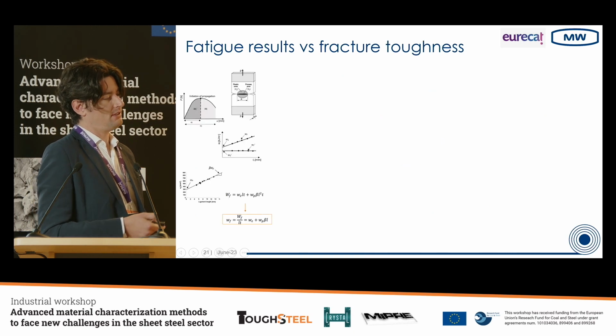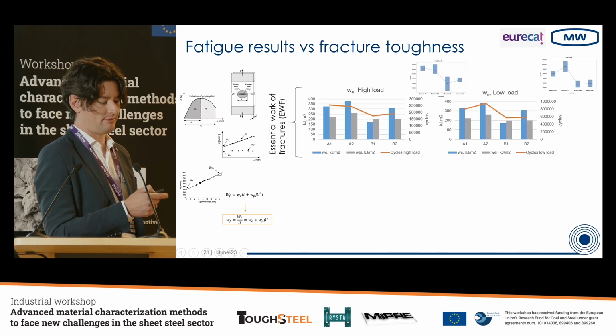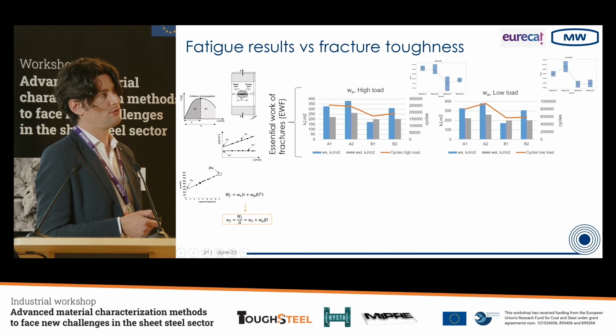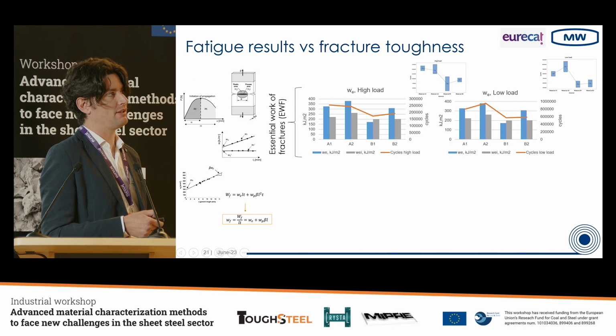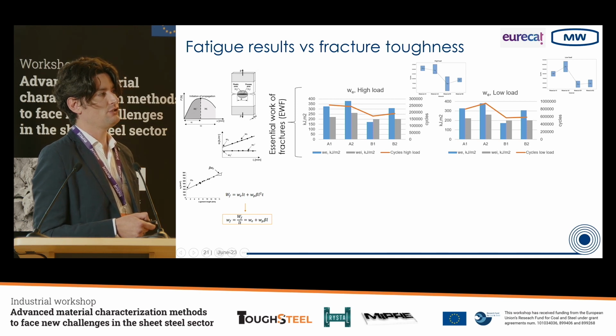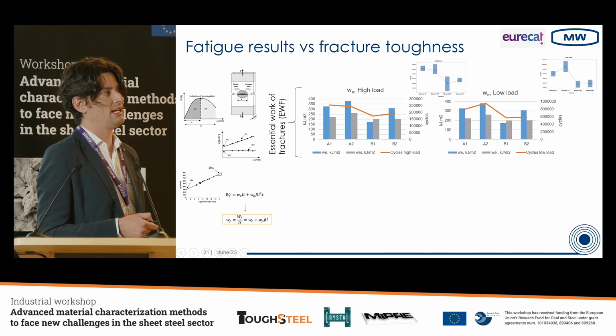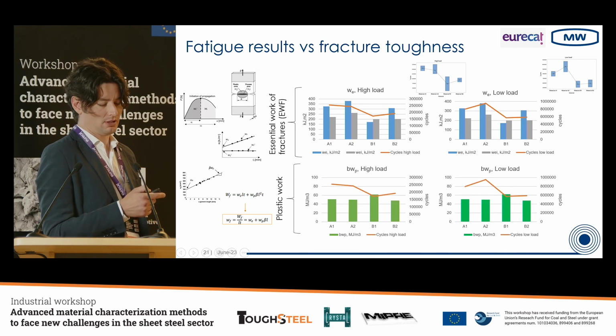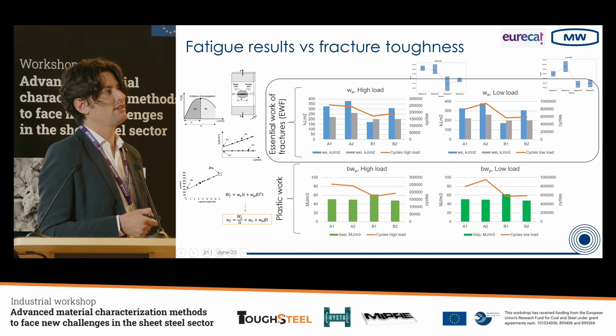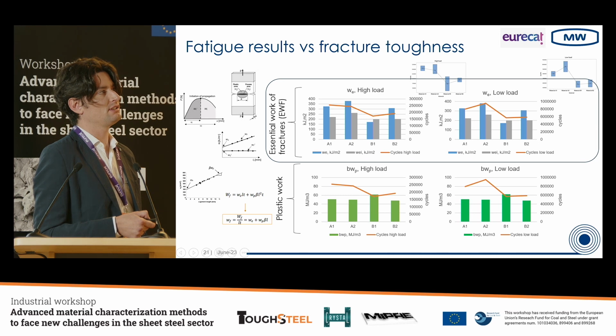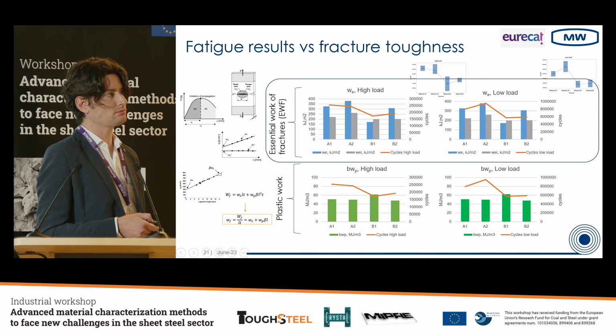And so this is the activity that we did with Eurecat. Here we have the essential work of fracture, compared with the fatigue in orange. For each high load and low load, we have the fatigue for material A1, A2, B1, B2, and also the plastic work. And it's visible that there is quite a good correlation between the number of cycles and the essential work of fracture at initiation, so the gray bar.